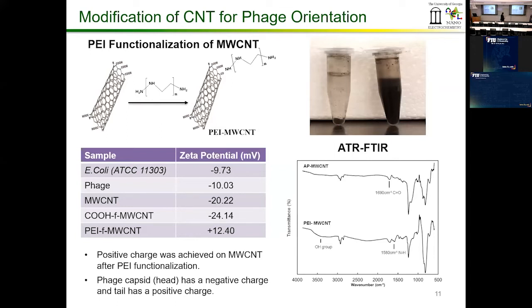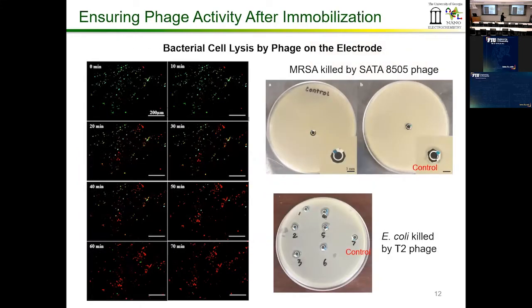And we did some ATR-FTIR measurements to make sure this functionalization has happened, and after that we also tried to put viruses on top of the surface to see if the viruses are not only attaching to the surface, but also retaining their activity, which means they're retaining their infectivity. You can see after putting it on the electrode, all the blue dots of the bacteria are present on the electrode, and slowly they're beginning to die. Within 30 minutes, half of them are gone, and by about 60 minutes, most of them are gone. So the virus retains its infectivity even after immobilization, which is important because naturally they will be infective only when they're in the solution mode.